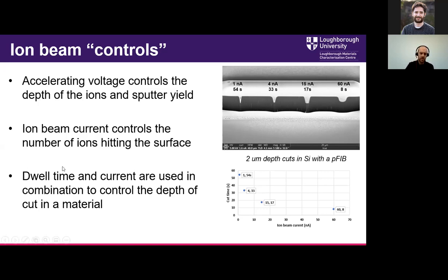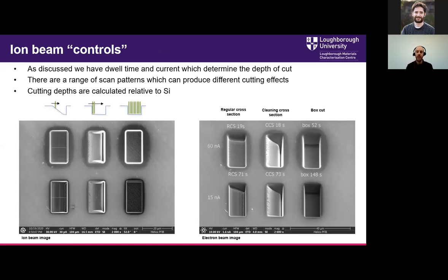And we can combine this with dwell time and how many times we raster over a surface to control the depth of a cut in a material. And we can start combining these different cutting functions to produce different shapes. So we can do things like staircase cuts where we try and minimize redeposition and make a nice clean edge, and also cleaning cross sections where we'd raster the beam across and bring it closer and closer to the surface, again to polish a surface, or just box cuts. And we can take this further, in fact, and start doing lithography and mill out all sorts of interesting patterns, maybe if we want to make microfluidic devices and things like that.